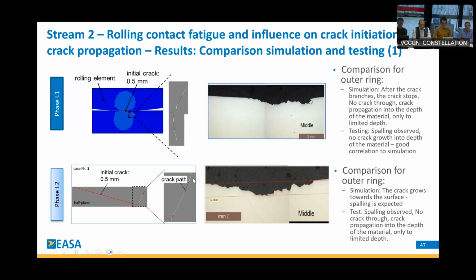For the phase 1-2, we have the same initial crack of 0.5 millimeter. Again, the crack path was simulated. You see it here, we would expect again spalling from the simulation. And you see it here where the arrow is the metallographic cutting of the sample. We see a spalling. The crack propagates only up to this final depth here. If you cut, you see these small cracks, and it is only limited, but there's no crack through. So the simulation and the testing also correlated quite well.